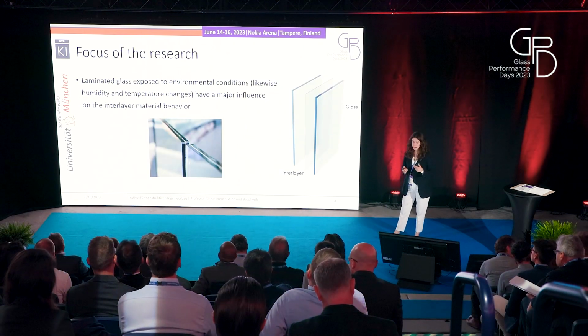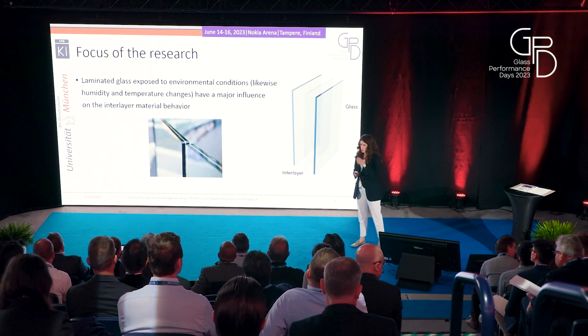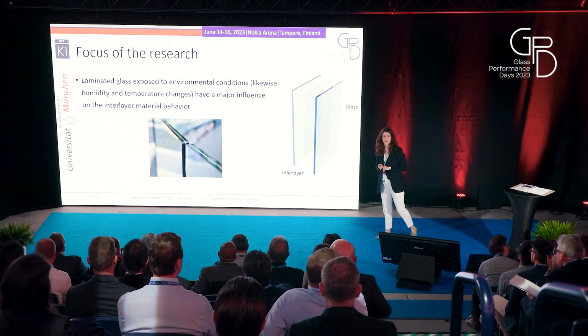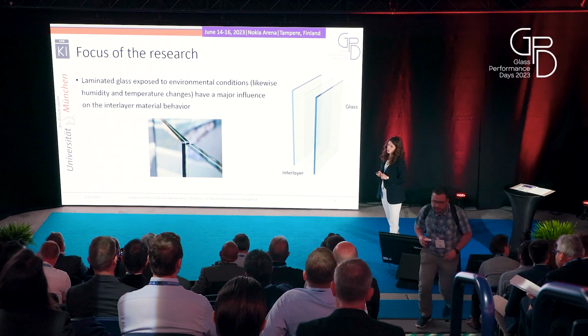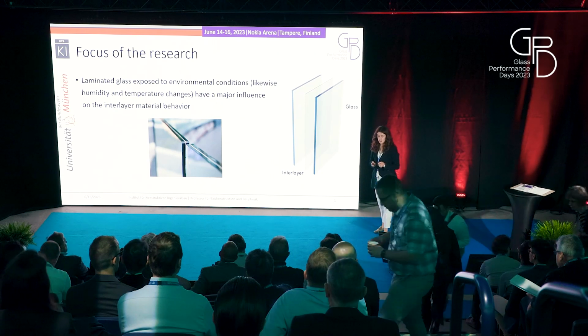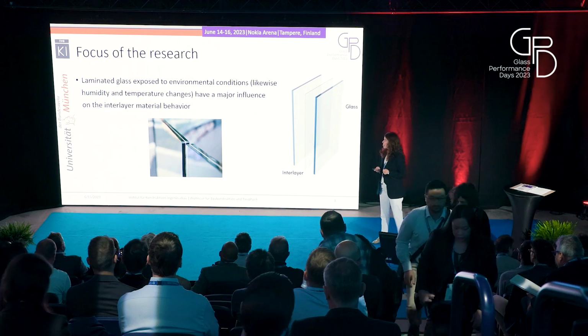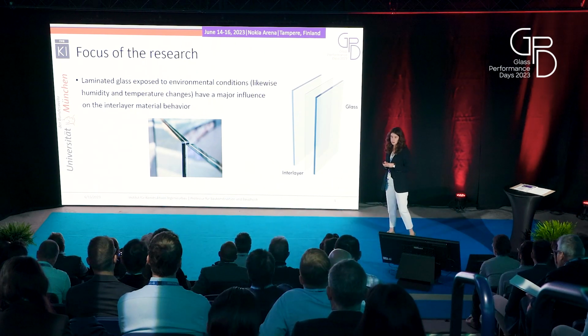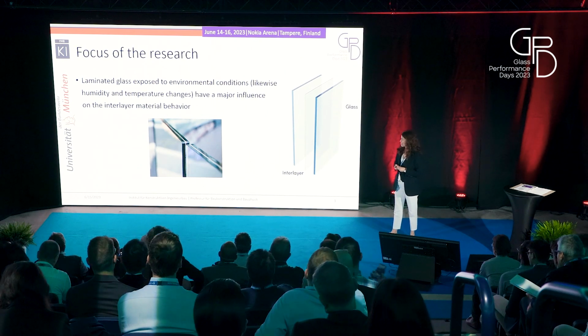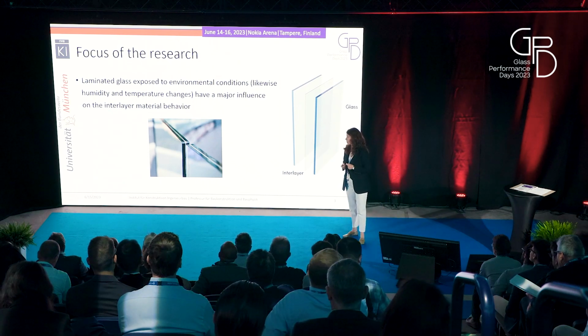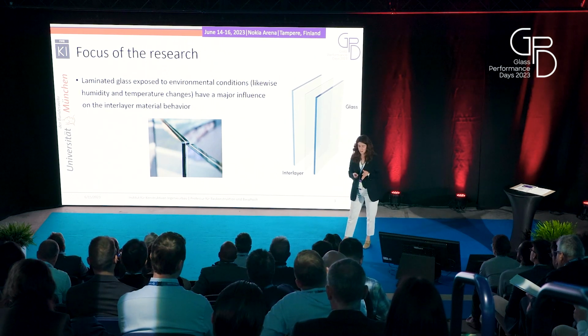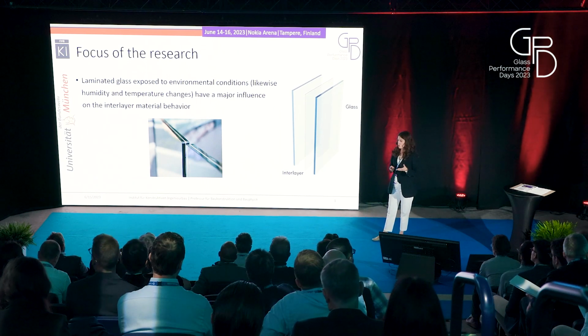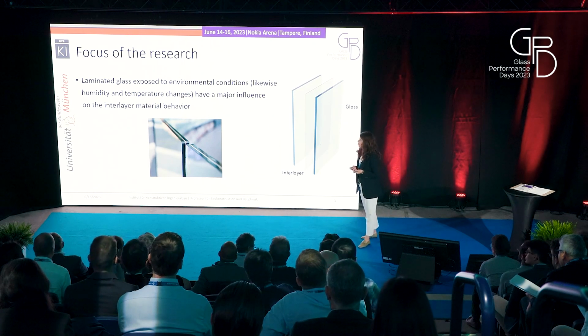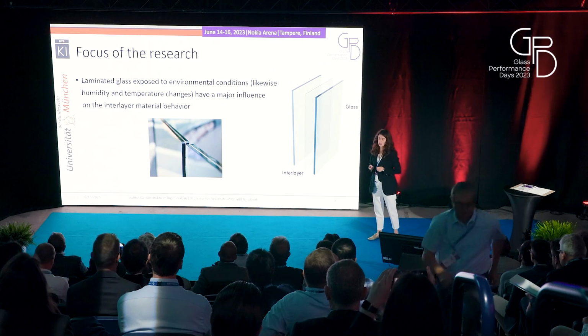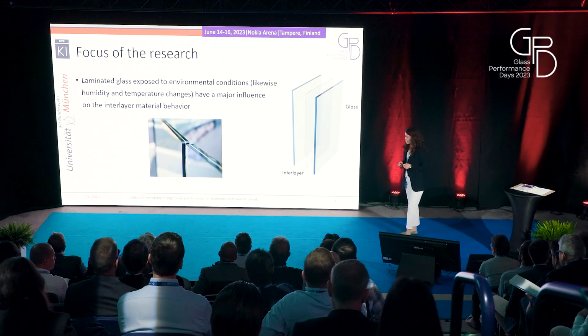As said, the focus of the research is laminated glass. When exposed to different environmental conditions, like humidity or temperature changes, there is a major influence on the interlayer behavior. In general, laminated glass is a composite of the glass and the interlayer, which makes it complex, because we all know that glass has a brittle behavior. It behaves linearly elastic until a certain point, and then without any announcement, it just breaks. That's in contrast to how the interlayer behaves. The interlayer doesn't have a linear behavior, it has a non-linear behavior. It's also a polymer, which means that the material model is either viscoelastic or viscoplastic, which makes this whole thing even more complex.